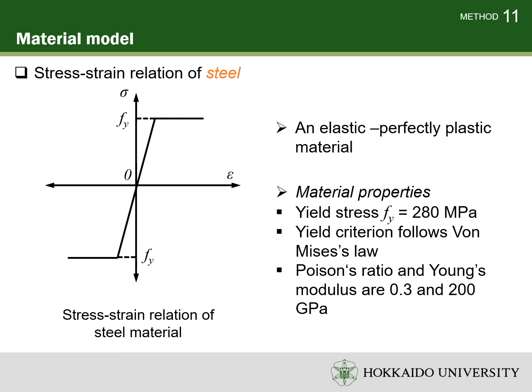Material model. The stress-strain response of steel material in the analysis is shown in this figure. Steel is assumed as an elastic, perfectly plastic material with a yield stress of 280 MPa. The yield criterion in the model is following the von Mises law. The Poisson ratio and elastic modulus of steel material are 0.3 and 200 GPa respectively.